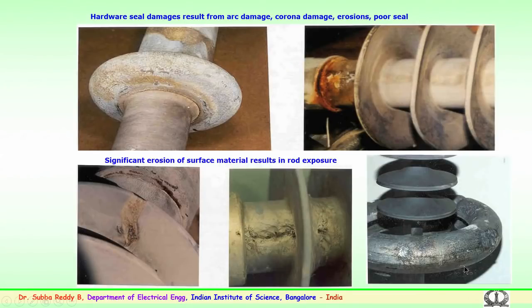There are further reports about the hardware damages. You can see here the corona control ring or the end fitting which is fixed to the insulator surface degraded over a period and becomes highly corrosive, and this leads to the failure of the insulators over a period of time. You can see again these failures of the corona ring due to the lightning surges or over a period of time in service, where failures have been noticed. Again here it is tracking or surface erosion which has happened in both the cases. This could result in the failure of the rod exposure.